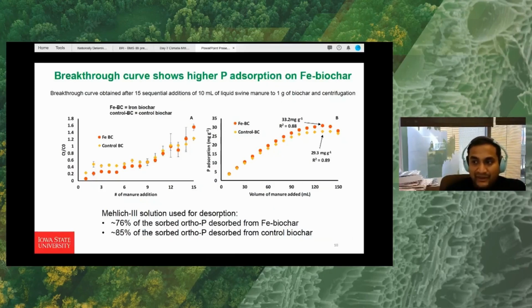So we have used the Mehlich 3 solution again for the desorption study, and we found around 76% of the absorbed ortho-P desorbed from the iron biochar, whereas around 85% of the absorbed ortho-P desorbed from the control biochar. This study suggests that the phosphorus absorption is happening in the high colloidal particles with the biochar. So when we did the desorption study, that colloidal particle together with the phosphorus came out into the solution.